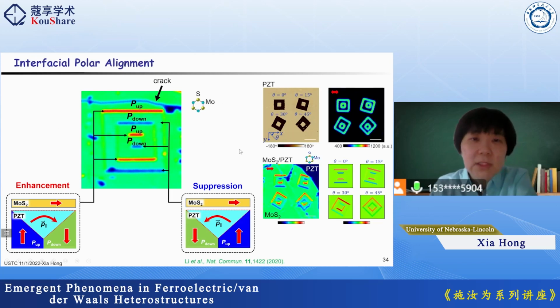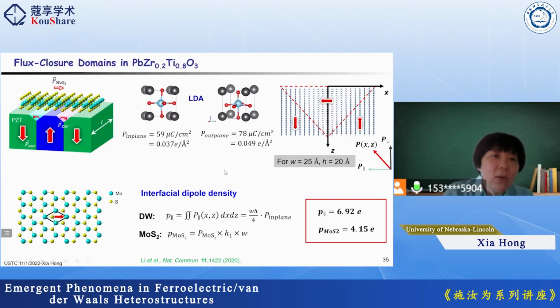Assume that the domain wall can generate a similar amplitude of SHG signal as the MoS2, and model the effect. What's shown here is the same flake of monolayer MoS2 put on domains written in different orientations. This is the electromagnetic theory modeling, and you can see the amplitude modulation can be well explained by this scenario. So microscopically, why is this the case?